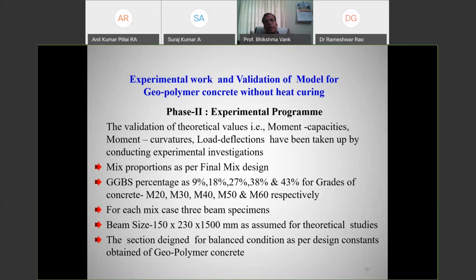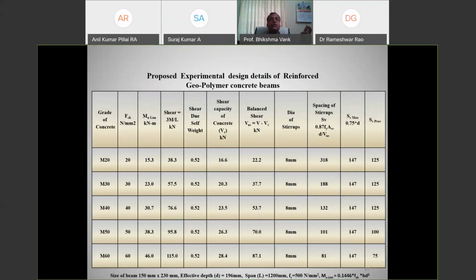Theoretical moments we get earlier with theoretical equations, and experimental moments we get after testing the beams experimentally under 2-point loading. These two need to be compared. That is the importance of this investigation. If you compare these two and they are near, then yes, the study is okay, the comparison is okay, the investigation is okay. You can use the geopolymer concrete for design. Like that, all the proposed experimental details of the reinforced geopolymer concrete beams have been obtained, for shear, moment, and all these.